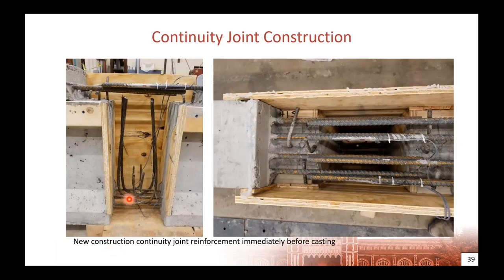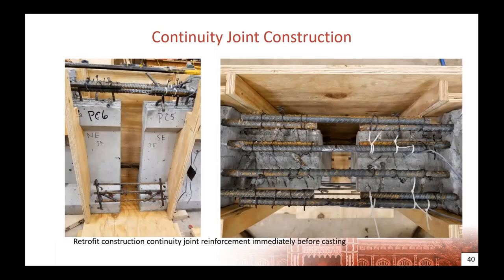So showing those strands extended into the joint, showing the overlap of the reinforcement from each side of the deck, and strain gauges placed on the reinforcement to measure strains during our load test. The same thing for the retrofit construction specimen. You can see the rebar studs here at the bottom, the straight bars extending across between the two flanges, and then the rebar lap splice at the top in the negative moment region.